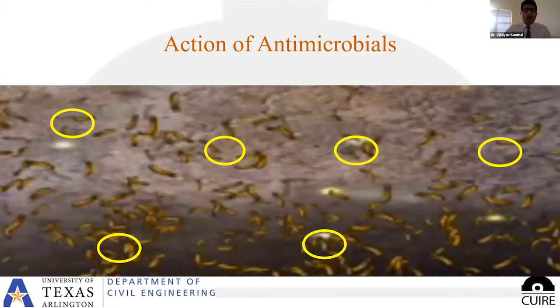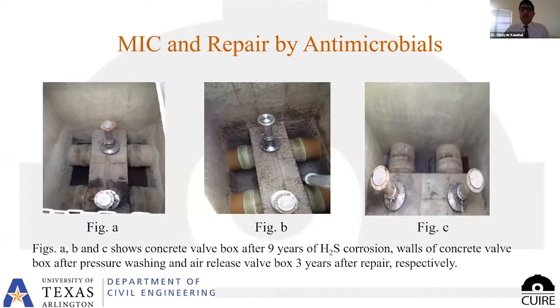So now how it's going to act is this way. As the Thiobacillus bacteria attempt to colonize the antimicrobial treated surface, they are met with an electrochemical shock with the help of this antimicrobial. And therefore, if there are no bacteria, there will be no acid produced, and as a result there is no corrosion.